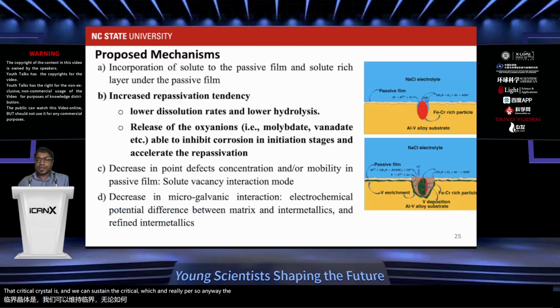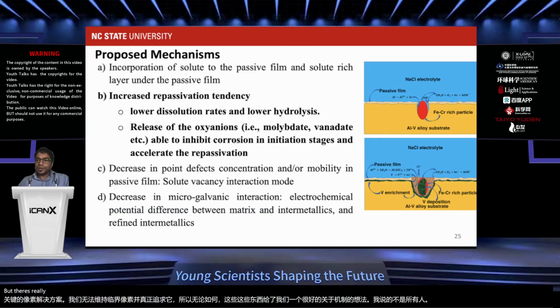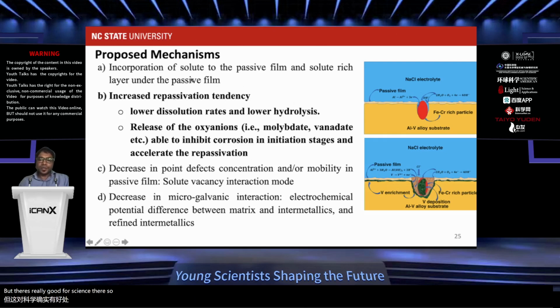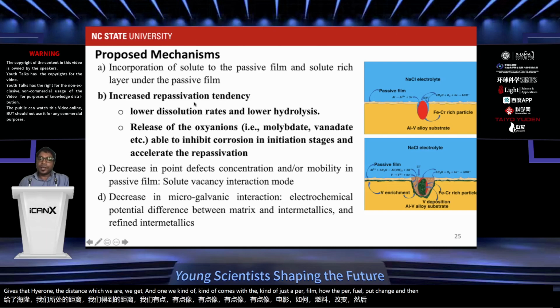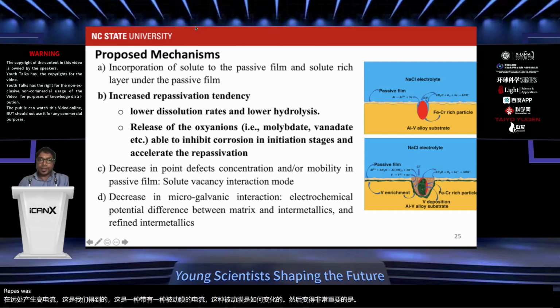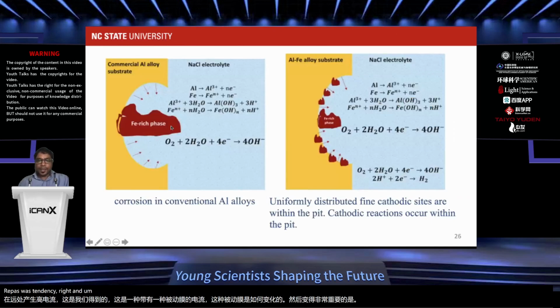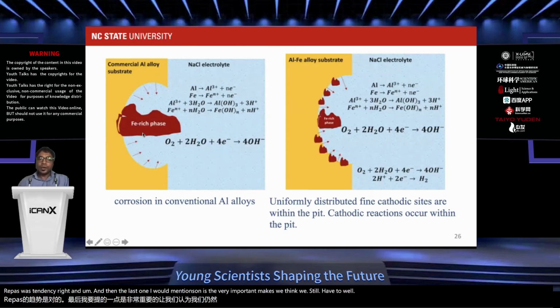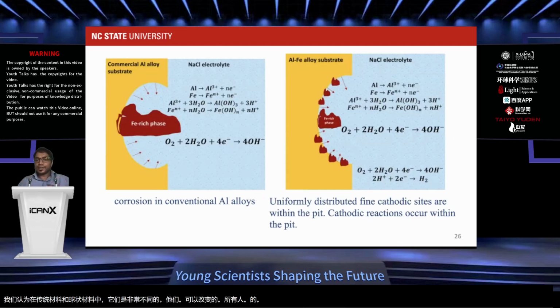So anyway, those things give us a pretty good idea about the mechanisms. I'm not talking about all of them, but there's really good fundamental science there. So we put together a bunch of proposed mechanisms for how this particular material gives the high corrosion resistance which we get. And one way comes with the passive film, how the passive film could change, and then the repassivation tendency becomes very important, right? And then the last one I would mention is a very important mechanism we think we still have to validate. We think that those cathodic particles in the conventional materials and in the ball mill materials would be very different, and they can change all the cathodic reactions and the chemistry inside the pit.